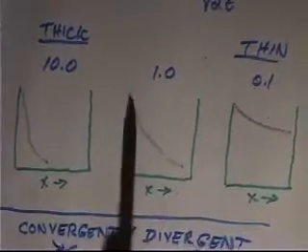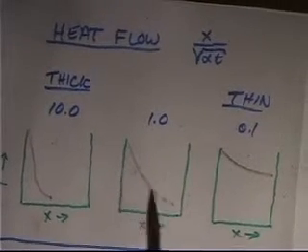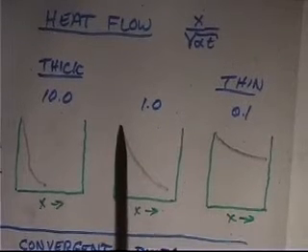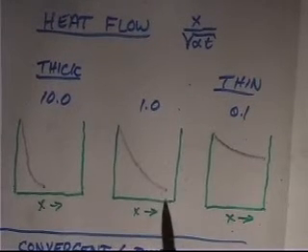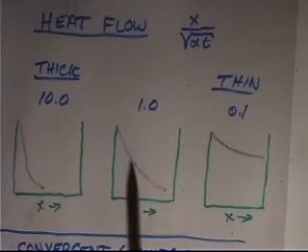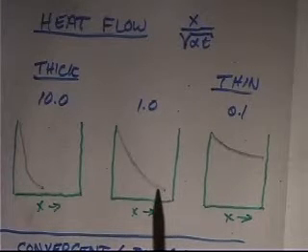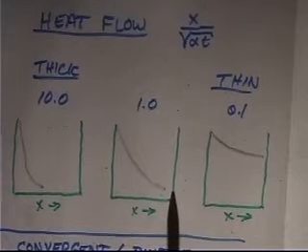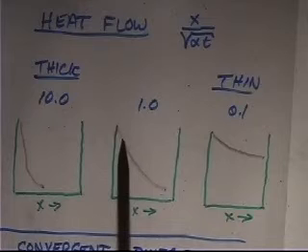I left there saying the thermal stresses were important. If the Fourier number is equal to 1, then for a material of some finite thickness X that is hot on one side, the heat will just start to show up on the other side. For the exact solution, an error function solution for a flat plate, I know that when the Fourier number is 1, the far side has raised its temperature by 10% of the maximum temperature on the hot surface.